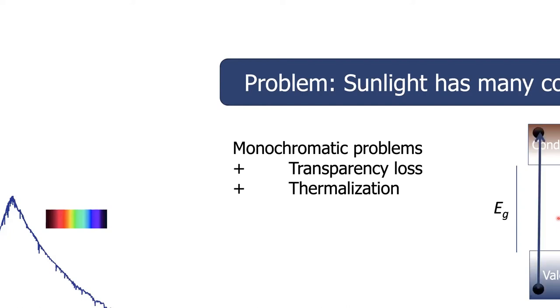But if we have a higher energy photon to take an electron from deep in the valence band, move it up to high in the conduction band, we quickly lose the energy. The electron falls down to the edge, the hole rises up to the valence band, and that's a loss. What that means is that our voltage is limited to be less than this band gap. So we need to have a high band gap if we want to have a high voltage.